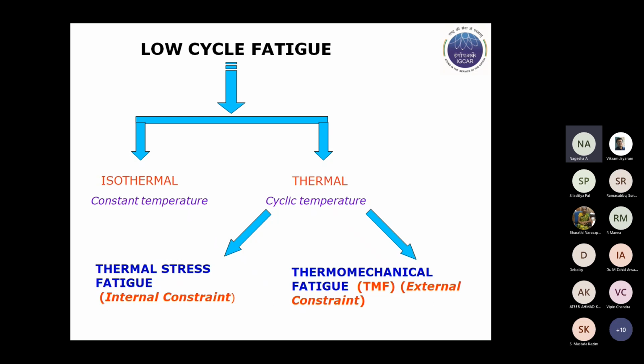So here in the thermal case, when you have cyclic temperature situations, there are two kinds of tests one can have. One is the thermal stress fatigue, which is the actual scenario in the high temperature components, because, as I have shown in the previous slide, the stress builds up by the internal constraints, the constraining forces offered by the bulk of the material. So this is the thermal stress fatigue, which is the actual situation that is happening in practice.